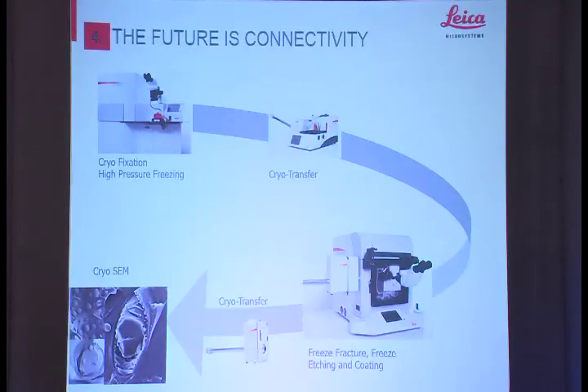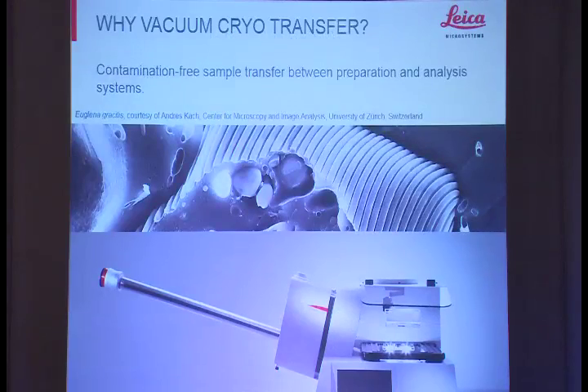So the Cryo SEM route involves a little system here called cryotransfer, and as you can see, this locks onto the freeze-fracture device and onto this transfer station. This enables us to take a high-pressure frozen sample into the cryotransfer station and then to any sample preparation system that we like, that has been equipped with a dock to take this. So this is a vacuum cryo transfer system. So it's cooled by liquid nitrogen and under vacuum. And this allows us to take us through to Cryo SEM techniques, for example.